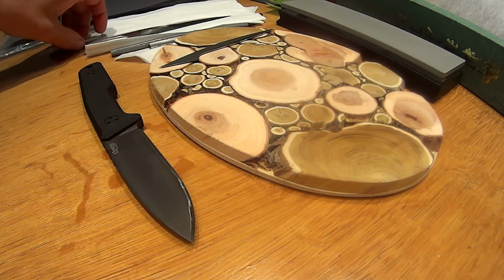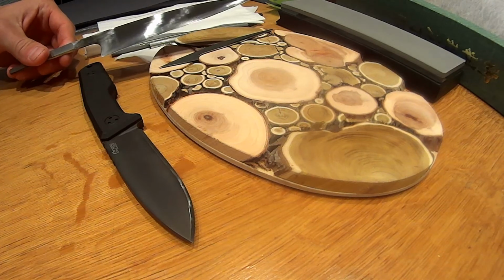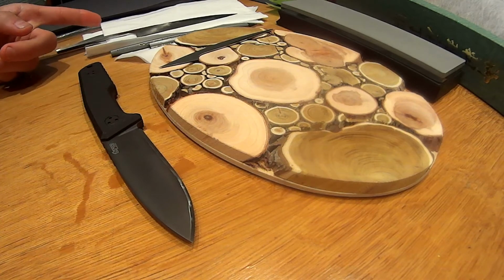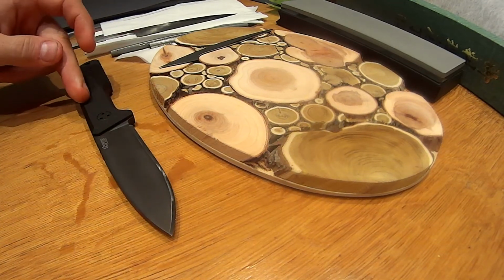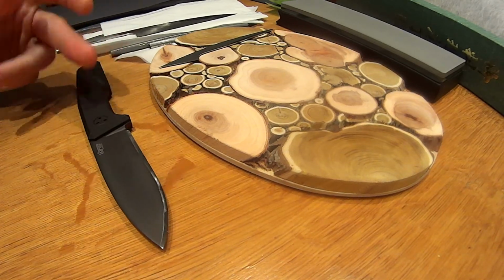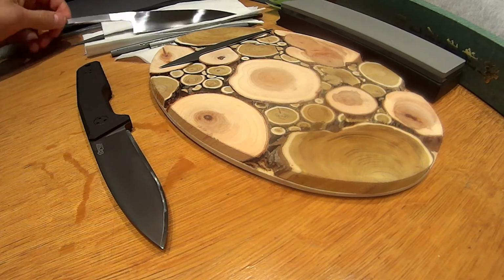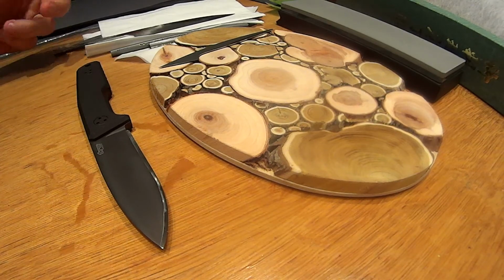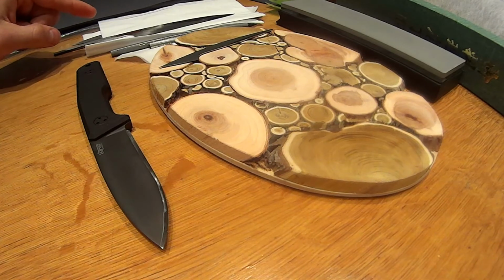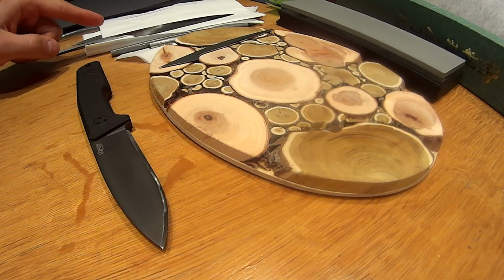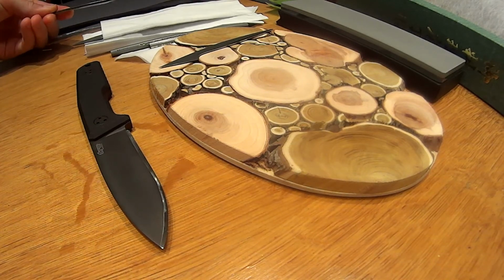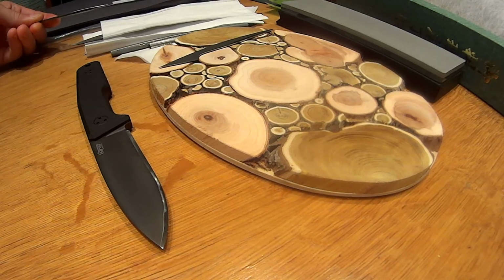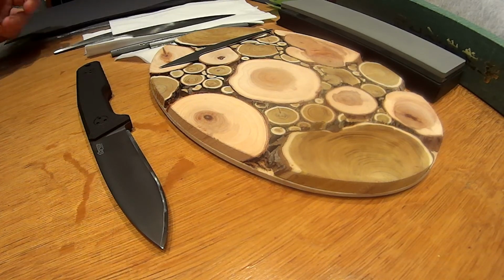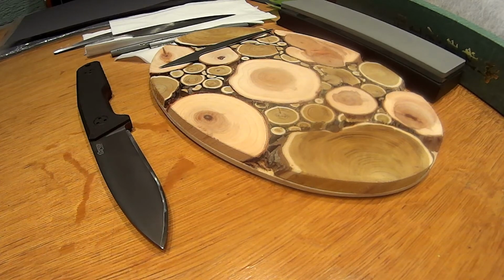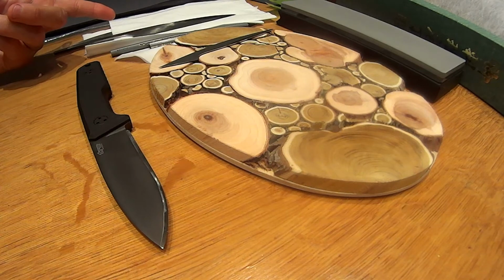On the other side, this steel is AEB-L, and it's been heat treated to 62 to 63 HRC, whereas this one, Vanadis 4, is 61, which is not a lot. You can take Vanadis to 63 plus with a decent tempering. So this is about 1.5 Rockwell higher, and usually I use a 20 degree, sometimes 15 degree sharpening angle, which is basically just a micro bevel, because I grind those almost zero. When I have an edge thickness of about 5 microns, then I put on a micro bevel. I polish and then sharpen the knife. And with this, I never experienced any microchipping.